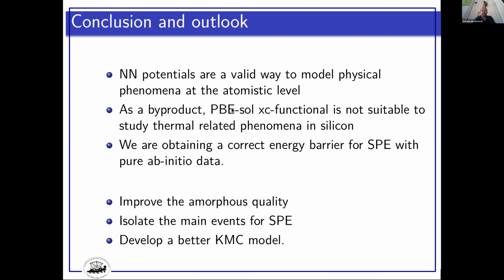So neural networks or machine learning in general is not a magic tool that will give good results even if the data that you are fitting on are not accurate enough. In this case, for the melting temperature of silicon, PBEsol is not a good exchange correlation functional, and PBE is more reasonable. Maybe some other functional is more realistic. So besides trying to speed up calculations using machine learning, we still need to develop better functionals to get a broader description of materials. And so I stop here.